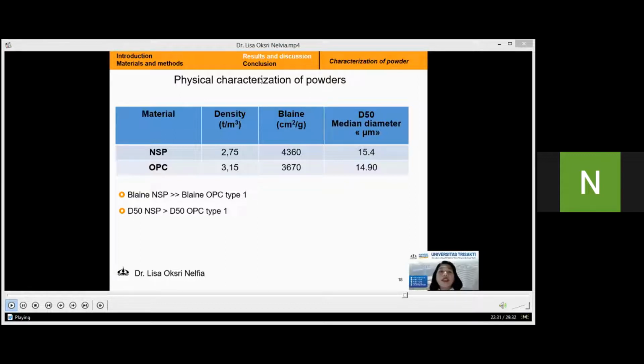The absolute dry density of NSP was smaller than the density of cement. In addition, the NSP specific area was higher than cement. Therefore, the nickel slag can be a supplementary cementitious material according to the literature. It also influences the compressive strength and the workability result.